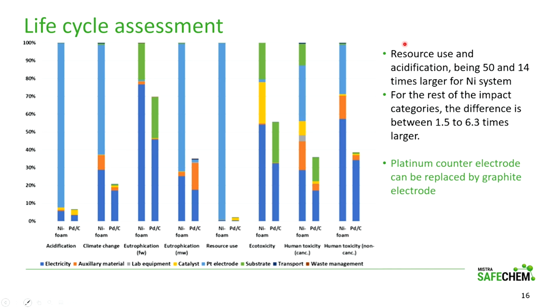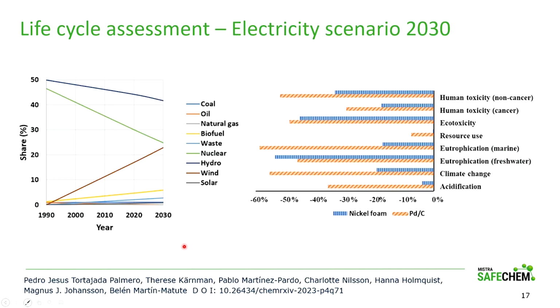But what we can also see here is that these big differences are primarily produced by the use of the platinum counter electrode. So replacement of the counter electrode would make this nickel system very similar to the traditional palladium on carbon. And this can be done, and we can use a carbon counter electrode, and then these impact categories are not so affected in the nickel system.